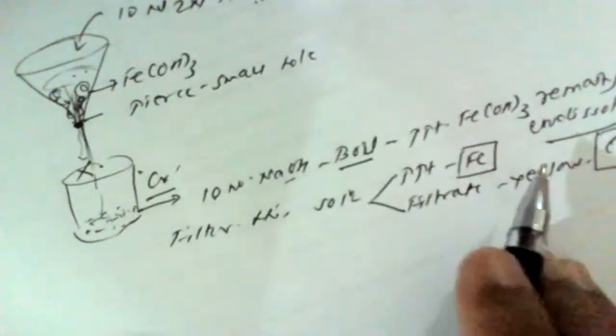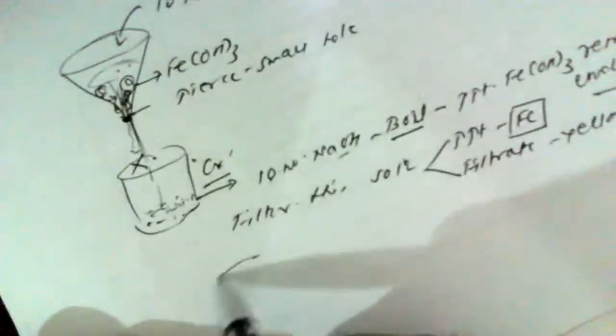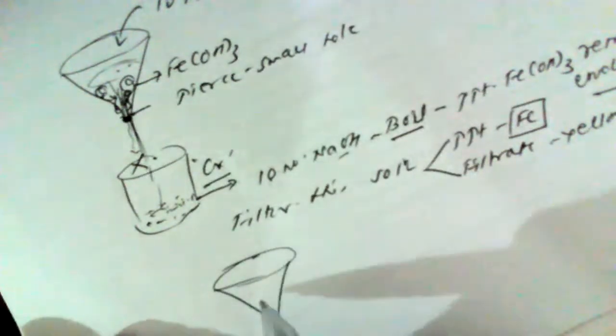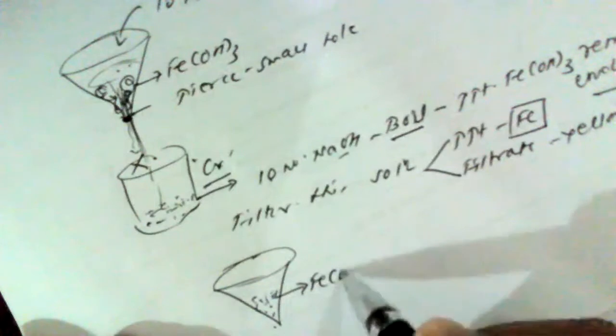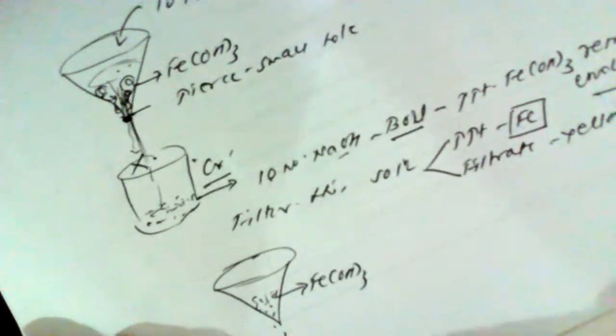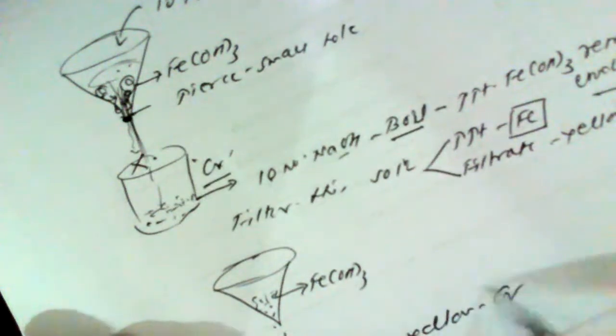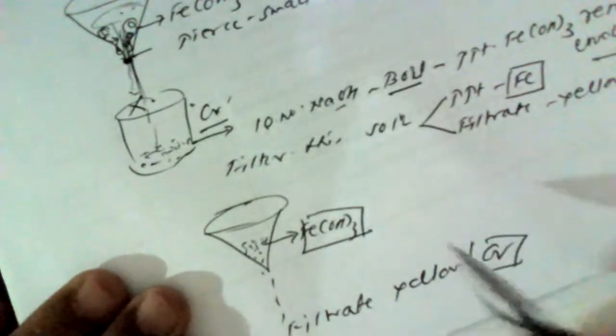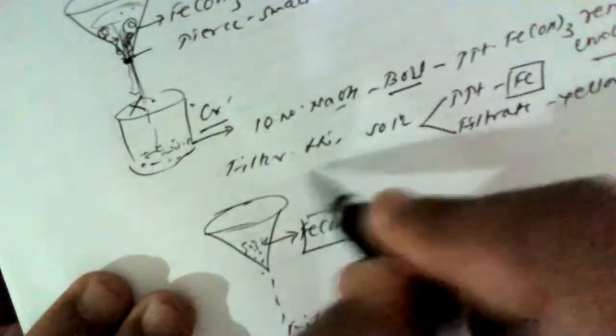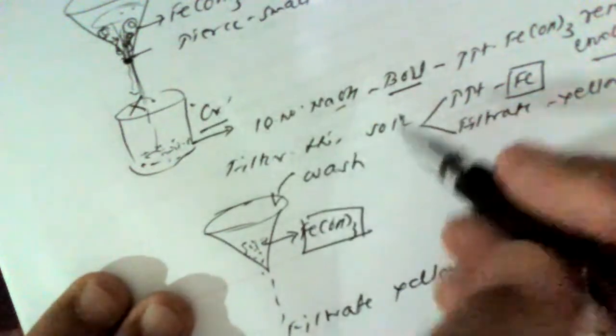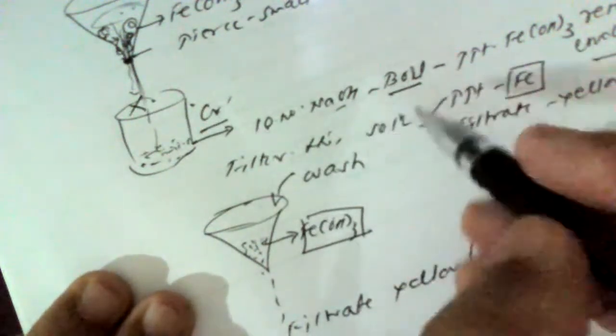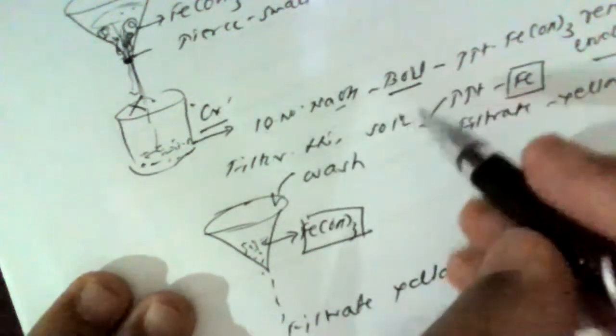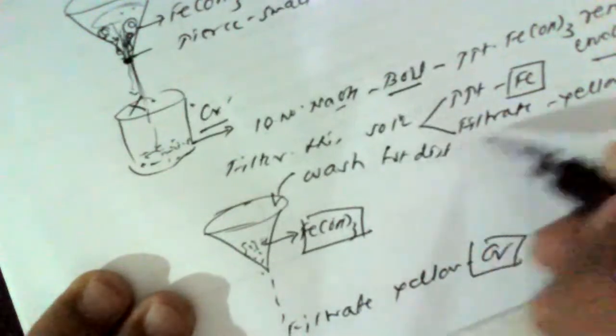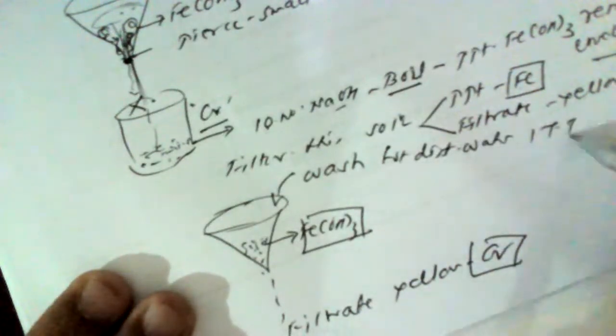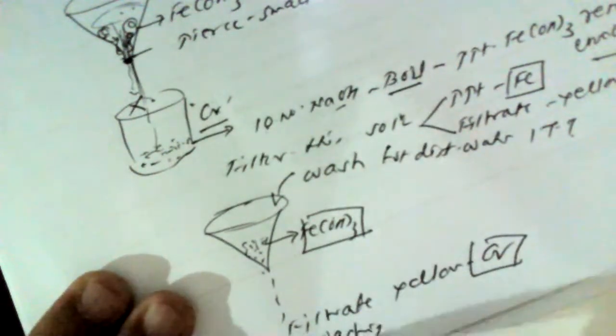Now to estimate this iron, say for example, this is our filter paper, over which the undissolved ferric hydroxide remains, and in the form of filtrate, which is yellow in color, chromium is obtained. So here iron is retained by the filter paper while the filtrate contains chromium. Now we have to wash this precipitate using hot distilled water, around 1 test tube, and we have to collect the filtrate and washings in a separate beaker.